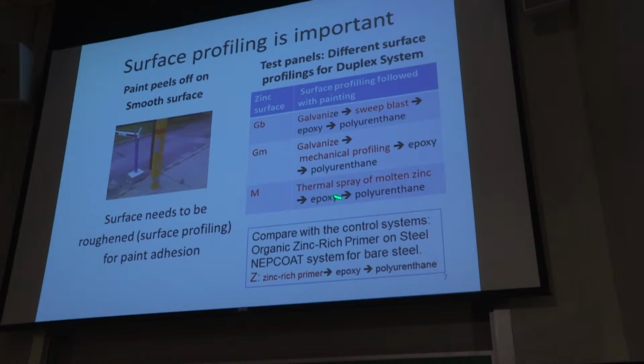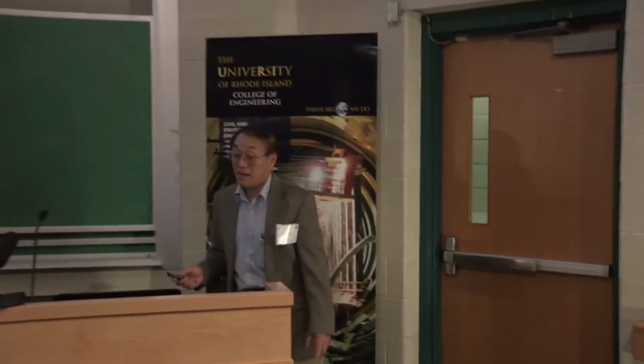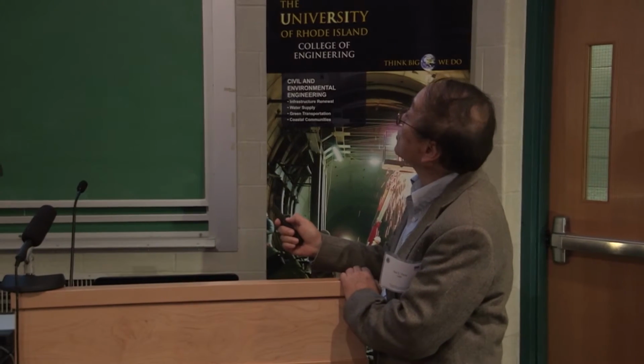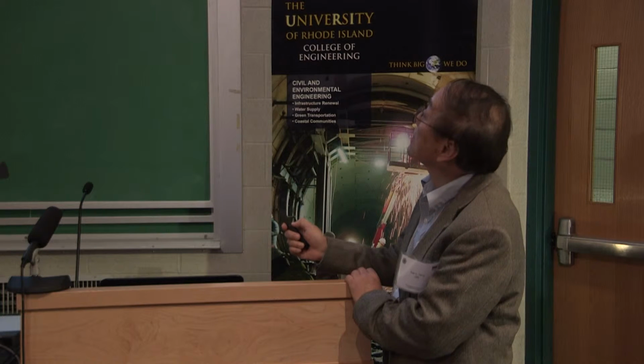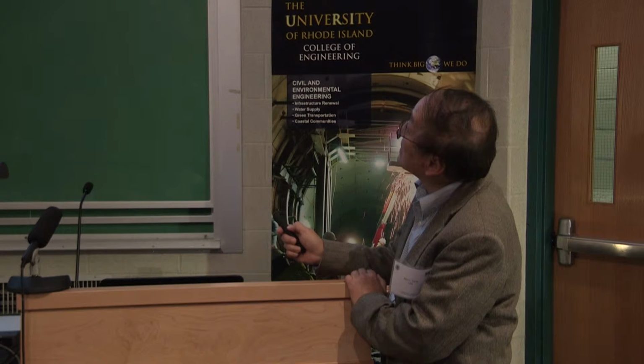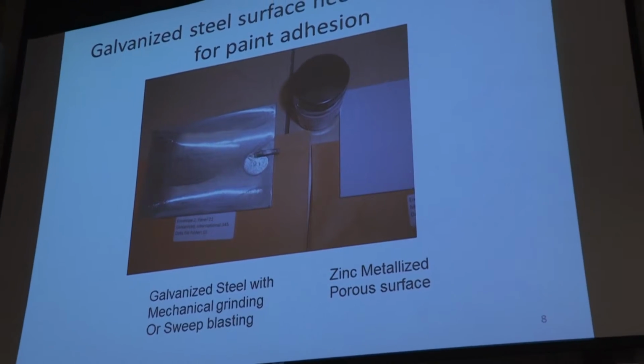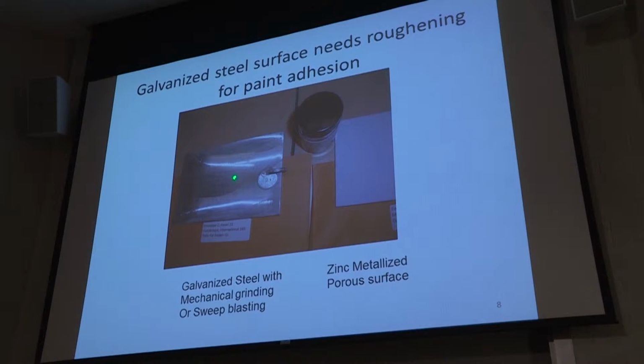And then the third comparison is the thermal spray, naturally a rough surface. These three types of samples were made into test panels, and we performed the adhesion test and the wetting comparison. So this is an example of the galvanized and mechanically roughened surface. This is with the roughening grinder wheel, so you can see a little bit of the tracks of this grinding. That is one of the methods to roughen the surface.